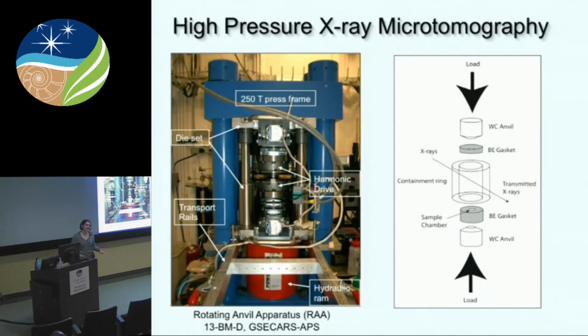All right, so to measure density, normally with crystalline materials you use X-ray diffraction, but there's no long-range order, so this becomes problematic with amorphous materials. So much of my PhD was spent developing high-pressure X-ray microtomography on the GSECARS beamline at APS. Fundamentally, this is a large volume press. It's relatively small for a large volume press. It's about this tall. But it consists of opposing anvils, and in between, inside of a containment ring, we have some gasketing material, and then the sample goes into the hole right in the center of the gasket. Pressure is generated by applying a load on the ends, and there are only 2 anvils because in order to do tomography, we need to be able to see through at least a minimum of 180 degrees of rotation. So having opposing anvils gives us a clear view all the way through the sample.